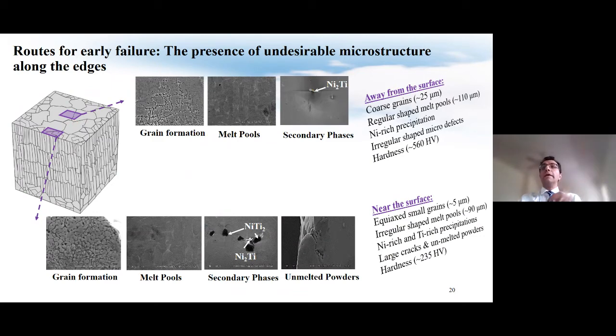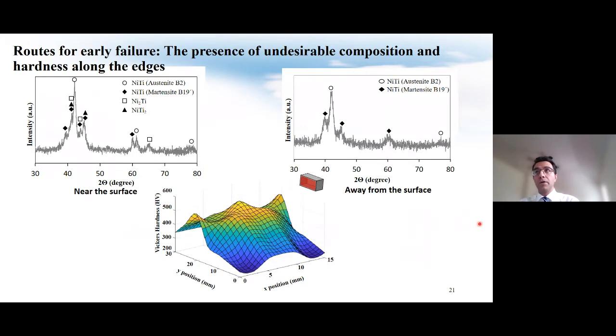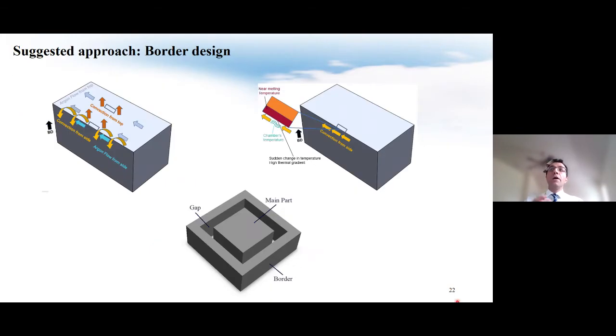Okay, so here we perform further analysis on the composition and hardness across the cross-section of the specimen, and we confirm that brittle precipitates are higher near the surface. Also, as expected, we observe lower hardness value for the area near the surface compared to the middle region. Our hypothesis was that the area near the surface undergoes additional convection mode, and that is why the cooling rate at the surface area is higher.